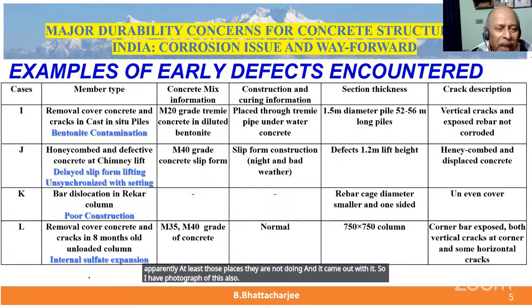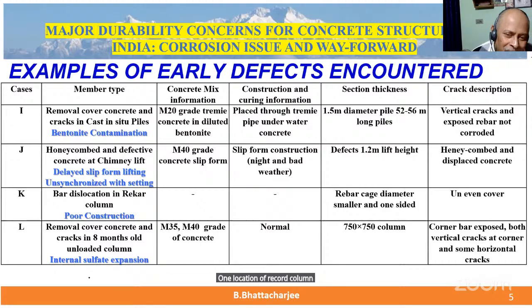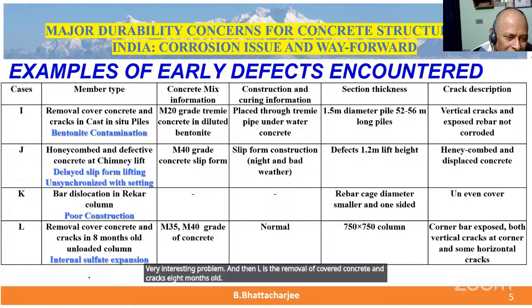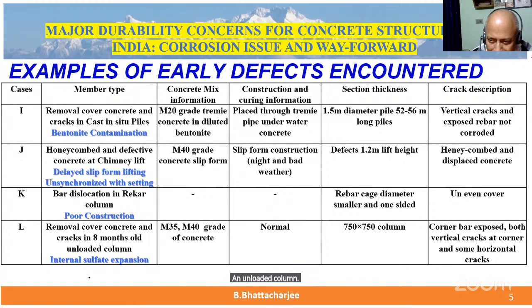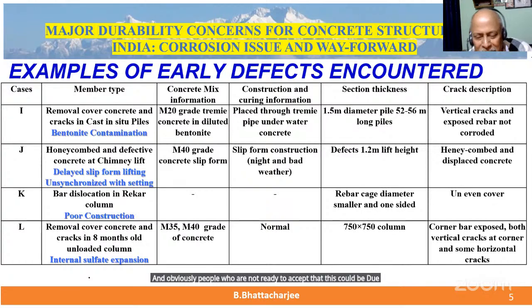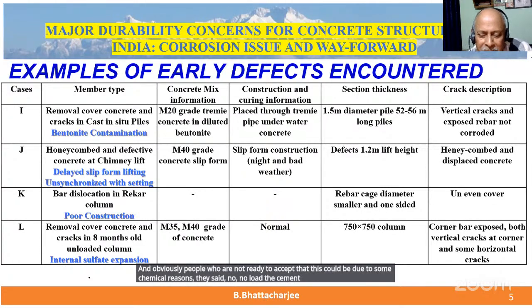Bar location of rebar in a column in a cooling tower that got dislocated. Very interesting problem. And then another is the removal of cover concrete and cracks in an eight-month-old unloaded column. There was no load. Not even the finishings were put in, but corners cracked, even rebars were exposed. And obviously people were not ready to accept that this could be due to some chemical reasons. They said no, low cement, strength problem, something like that.